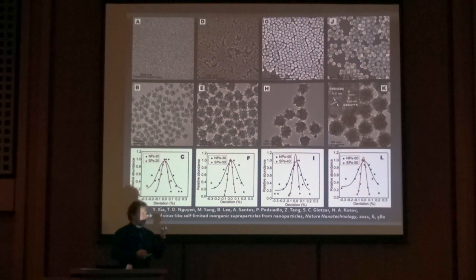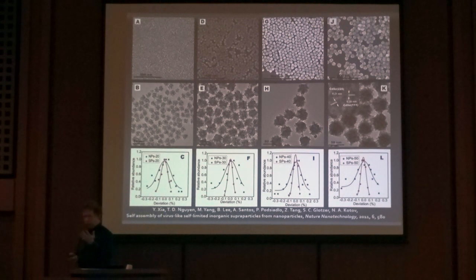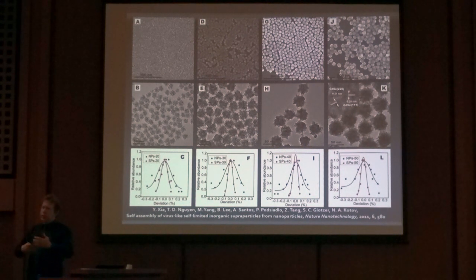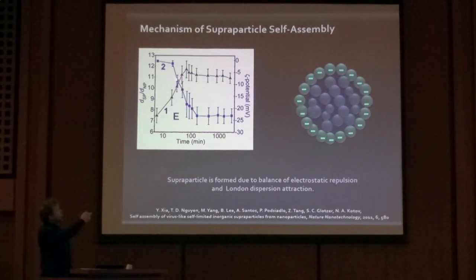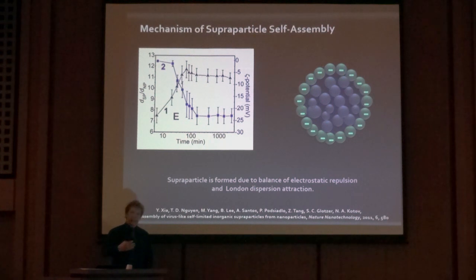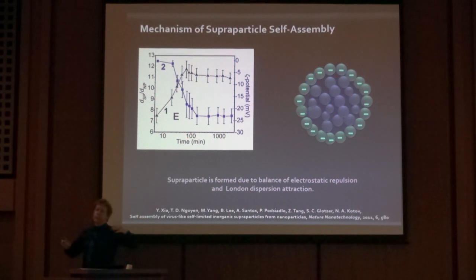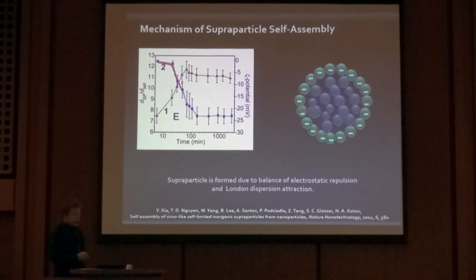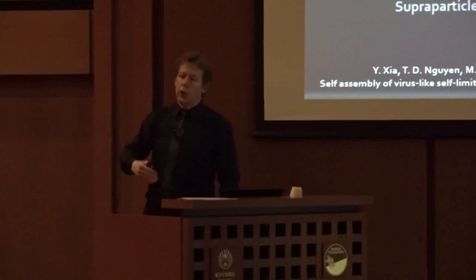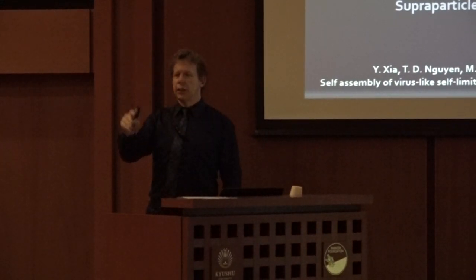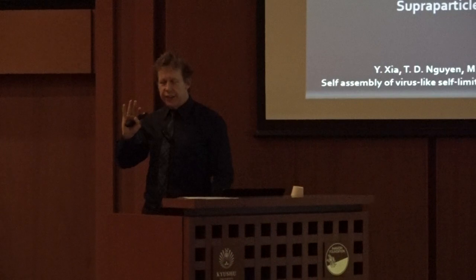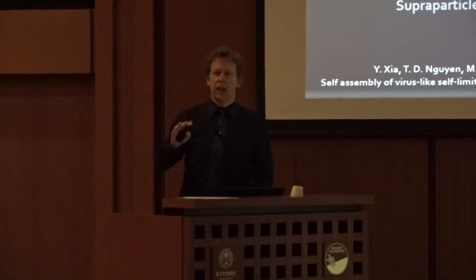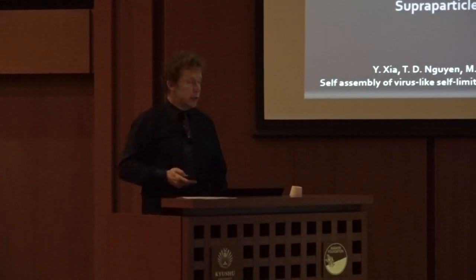polydispersity. For several days, I was kind of puzzled by that. Is it something like a magic cluster or some other type? Turns out quite easy. What we observed later on experimentally by using the zeta potential measurement is that as the particles assemble, they increase their zeta potential charge. And that leads to thermodynamic control of the particle size. Just like in micelles, there is nothing very different from that here, except the fact that the attractive forces are van der Waals and the hydrogen bonding.